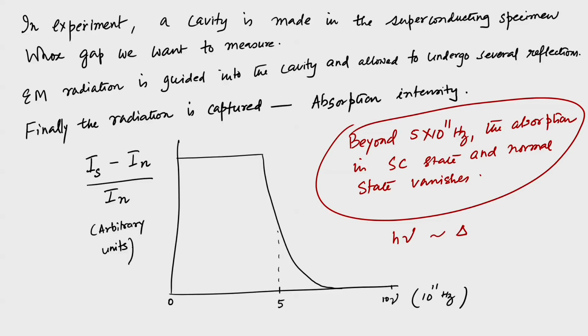It is notable to mention that similar absorption edges are also seen in semiconductors. However, the gap in semiconductors is typically 3 orders of magnitude more, or 1,000 times more than that of the superconducting gap. In silicon it is about 1.1 electron volt, in germanium it is about 0.8 electron volt, and hence the absorption edges are seen at much higher frequencies, because the energy gap is larger. So, basically this conclusively tells us that the magnitude of the gap can be determined from the absorption of electromagnetic radiation. Let us see one more experiment that also measures the gap.